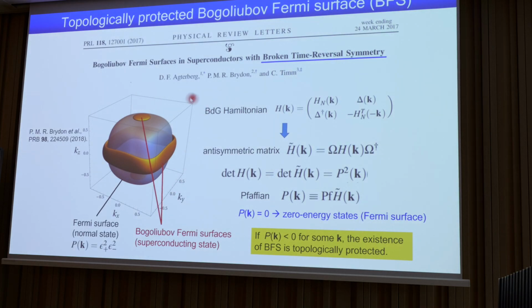They considered the time reversal symmetry breaking state. I don't want to go into detail since he's here, but I want to mention that broken time reversal symmetry is not a sufficient condition, it's a requirement. The actual requirement is that the Pfaffian should be negative at some certain k. Then these Bogoliubov-Fermi surfaces can be topologically protected. That's actually very interesting.